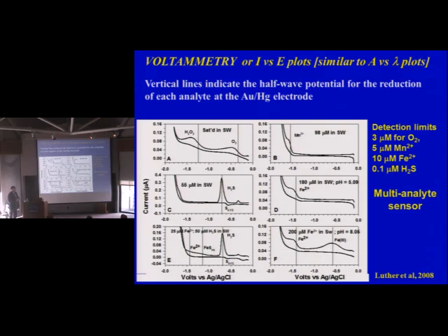iron, and 0.1 for H2S in seawater. They're a little bit better in freshwater, which is what I'm going to actually focus on today. We don't have standards for the iron 3 or for the FeS, because they're nanoparticles. The other thing is that every iron 3 ligand complex has a different peak potential. So you can't actually quantify this, because if it's a different organic matter, the current versus concentration sensitivity curve varies. So that gives you a little bit of an idea.